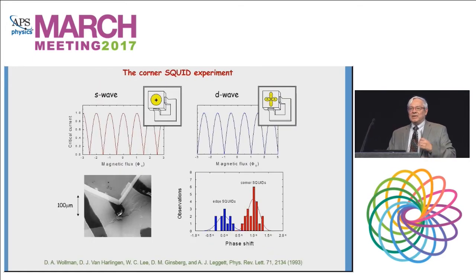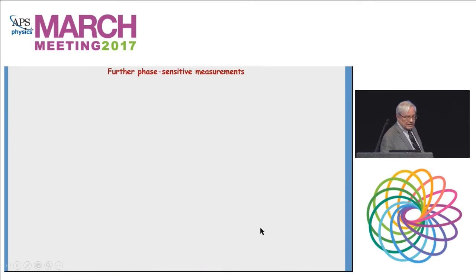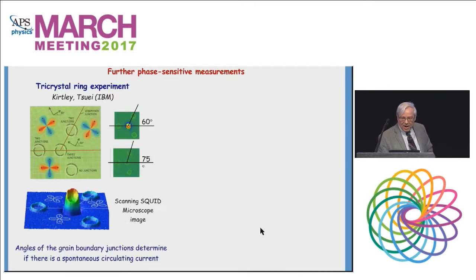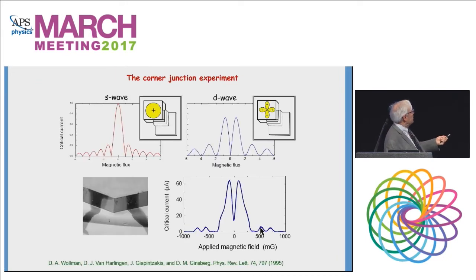If you do it for a single junction, the Fraunhofer pattern modulates into a very distinct pattern. So experimentally, we did the experiment on SQUIDs, and you can see the phase shift here, indicating D-wave superconductivity over here. And you can do it in single junctions and see this very precipitous drop in the critical current, which is a strong signature of d x squared minus y squared symmetry.